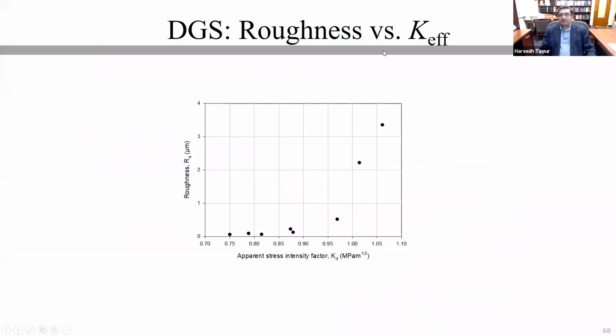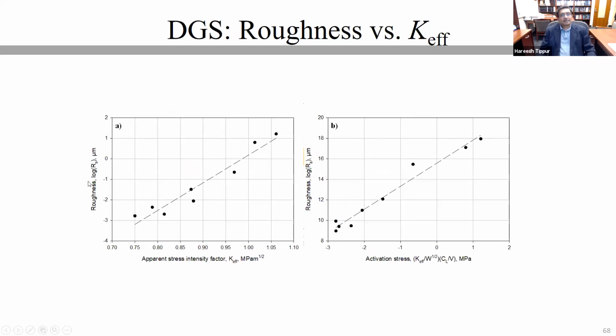So we tried to plot roughness as a function of the effective stress intensity factor. Lo and behold, we seem to have some kind of a power law type of behavior. To confirm that, we plotted roughness as a function of log of that quantity, as a function of your effective stress intensity factor, as well as this sigma hat, or the activation stress that I was talking about. And both of them seem to show some sort of a linear response, and this is where we want to go and explore this a little bit further in our future experiments.